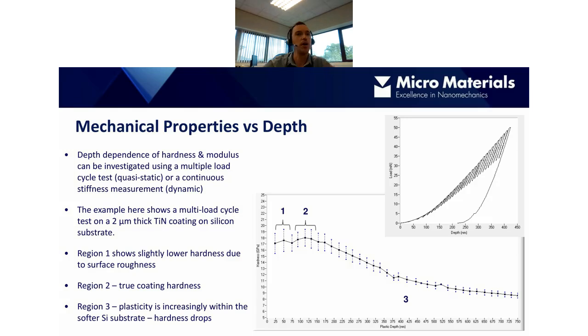So in the example you can see here, this is a 2 micron thick titanium nitride coating on a silicon substrate. And we can see the hardness here. Okay, so we have a peak hardness of around 18 gigapascals in this region. And you can see as the load increases, as the depth increases, we get an increasing influence from the silicon substrate, and the hardness then decreases and essentially just tends towards the hardness of the silicon itself.